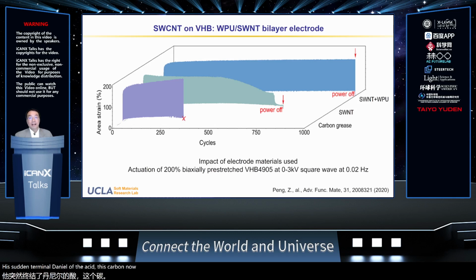With the carbon nanotube electrode, it lasts longer, but there's a problem because the carbon nanotube has sharp tips. Those sharp tips can cause arcing of the air around them. So what you see here is that with the SWNT electrode, the strain goes down over time. It does not fail terminally and suddenly, but the strain goes down because more and more of the CNT coating area gets burnt off or healed. Eventually you lose the active electrode area.